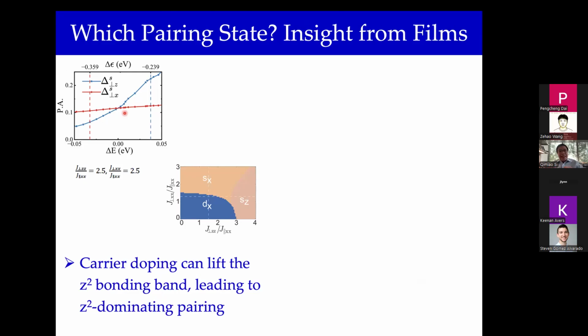But unlike in the bulk systems when you apply pressure, where all the lattice constants are reduced, here because it's a strain, the C-axis lattice constant is increased. And so that makes these small details, like the crystal field separation between the 3d x-square minus y-square and 3d z-square orbitals, more variable.